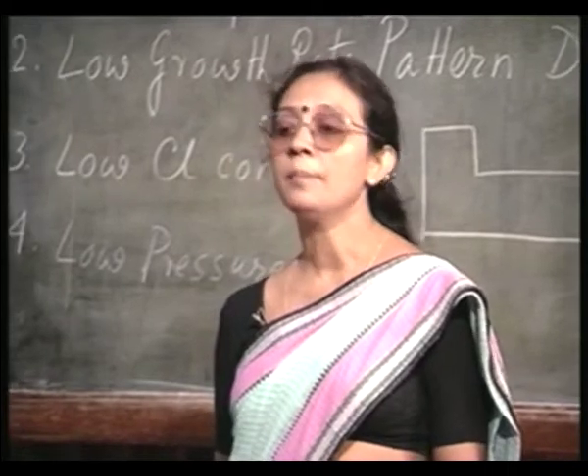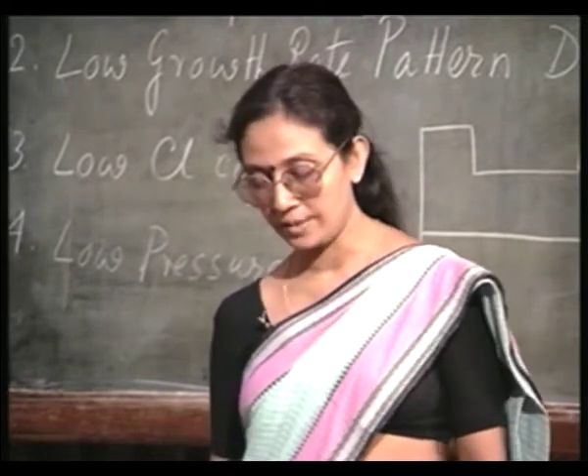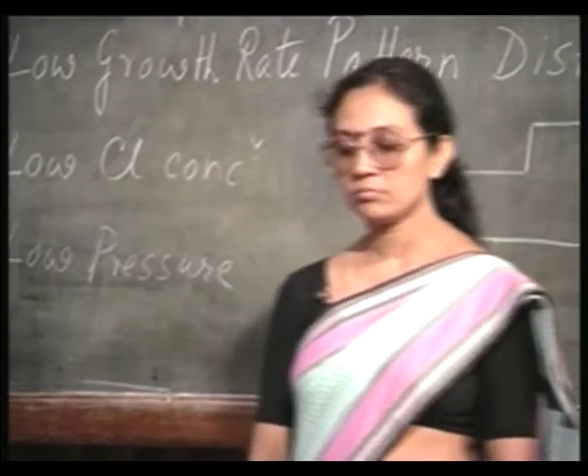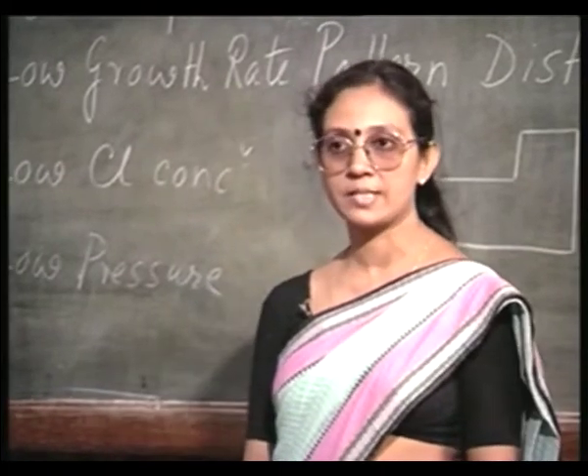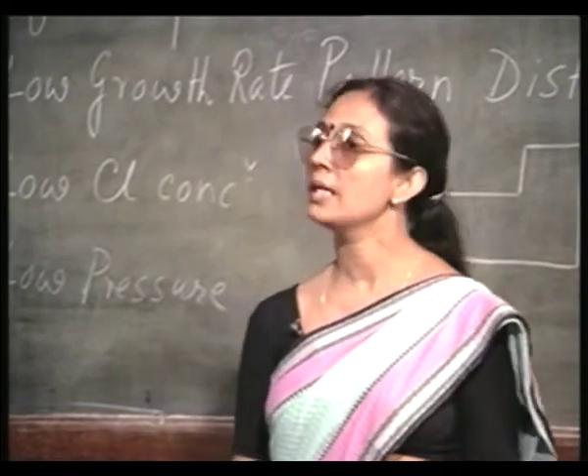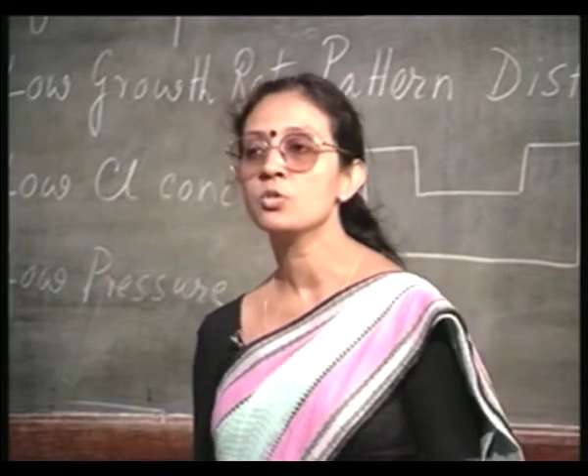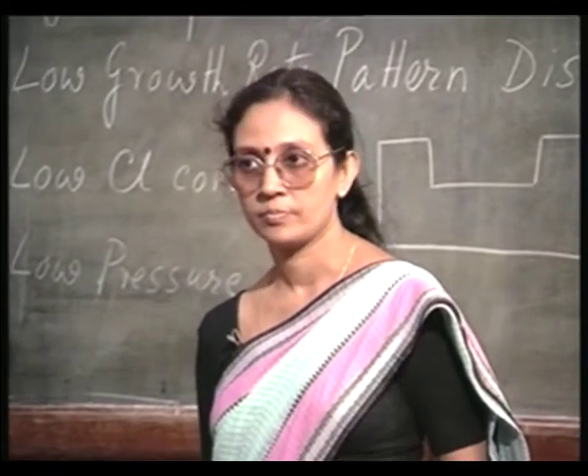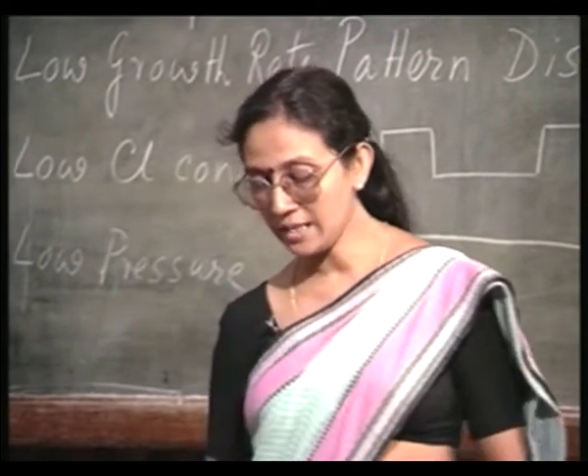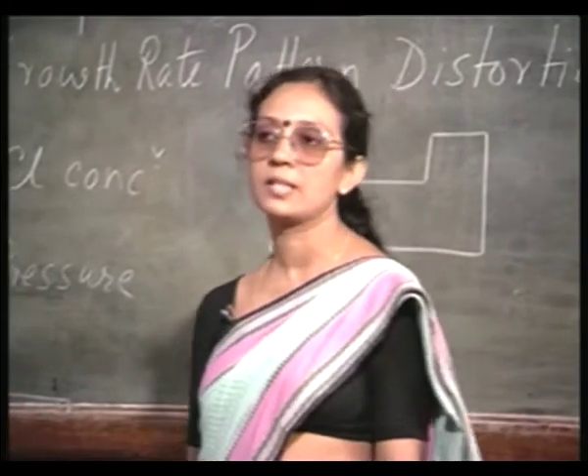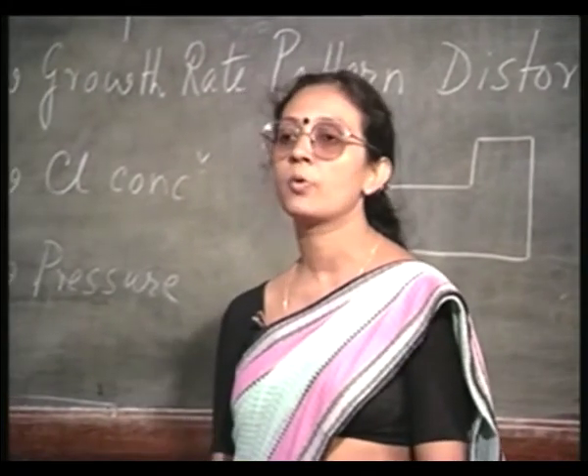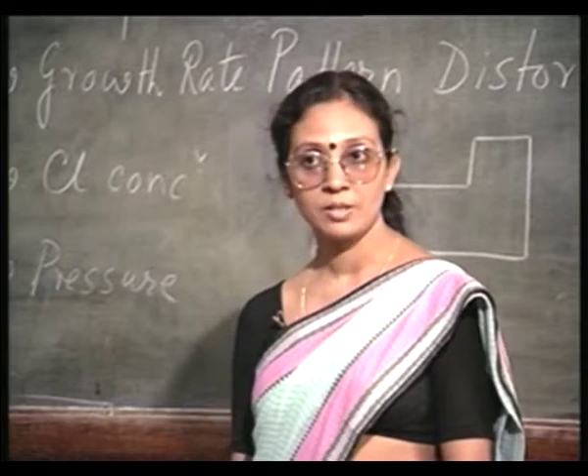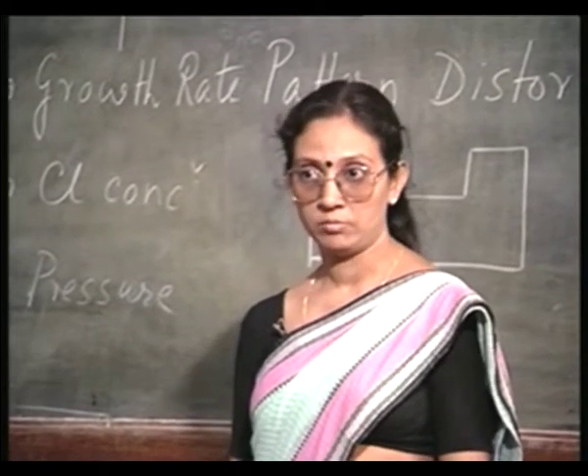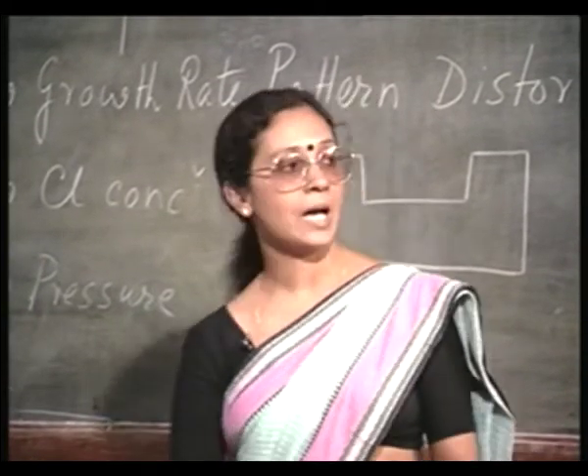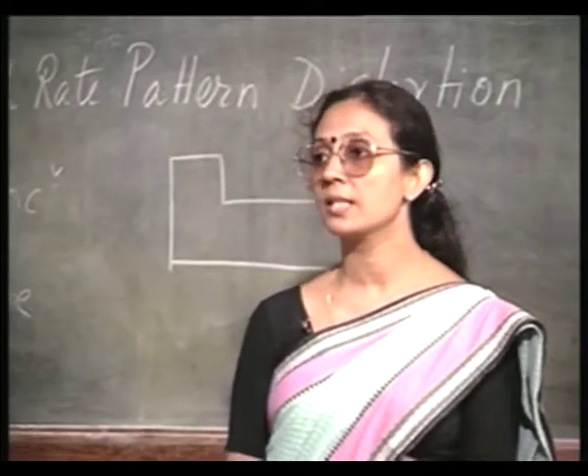See, if you remember, in the silicon crystal, the silicon spacing was related to the lattice constant. The value was 2.35 angstrom. On the other hand, the silicon oxygen silicon spacing is 3.05 angstrom. They are not equal.